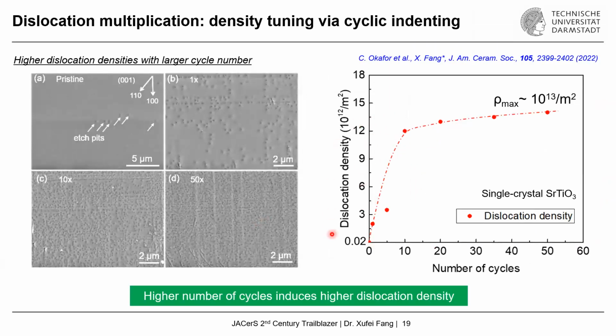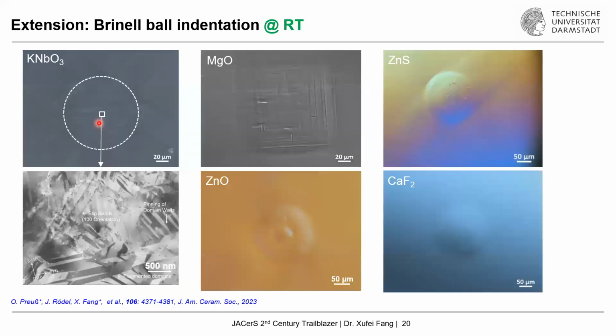So we plotted the dislocation etch pit density as a function of the number of cycles, and we saw that there is almost a 1,000 times increase in the density compared to the reference sample. And also there seems to be a saturation after roughly 10 cycles of indentation. We would like to point out that in this case, dislocation multiplication is happening, because we have a handful of dislocations in the beginning and they multiply and generate many, many more dislocations, which is very helpful for our dislocation-based mechanical and functional studies at a later stage.